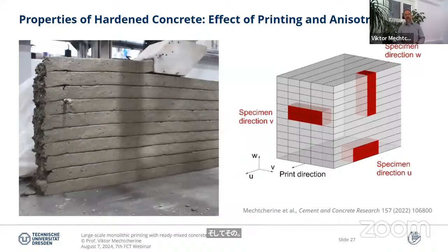When we print the material, after a while it hardens, and of course we need to know what properties we achieved. And in this case, it's really important to figure out in which direction we need to test. Basically, we have some heterogeneity and anisotropy due to the joints, as you see here. The joints are usually a little bit weaker than the rest of the material, the bulk material. And if you have many filaments deposited one beside the other, you might also need to take specimens in this direction. In this case, two directions are fine. So the direction of printing would be direction U as shown here, and direction W, right? For these two directions, I'll show you some results.